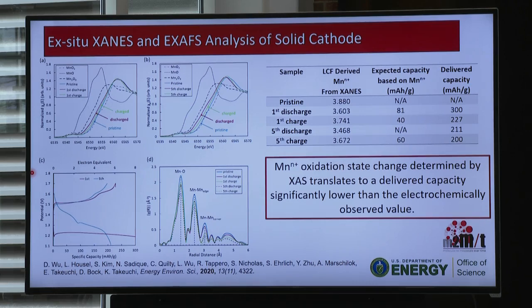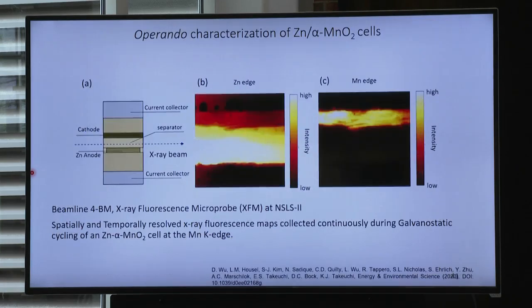And while in the vanadium case, the electron count added up, we can account for the oxidation state of the vanadium. In the manganese oxide case, we could not. We're getting more electrochemistry than the oxidation state change of the manganese oxide accounts for. So Kenna had a very clever suggestion and said, look, what you've got to do is study this operando. You've got to look at the cathode, but don't look at the cathode in isolation.